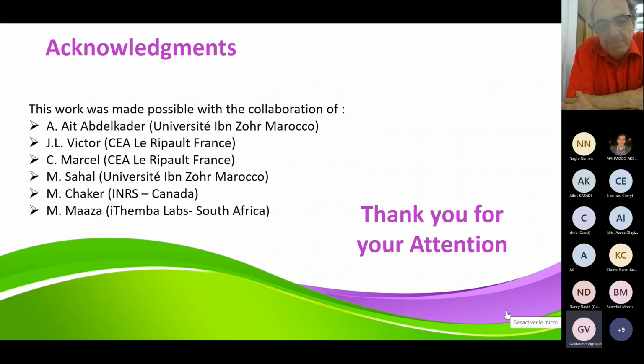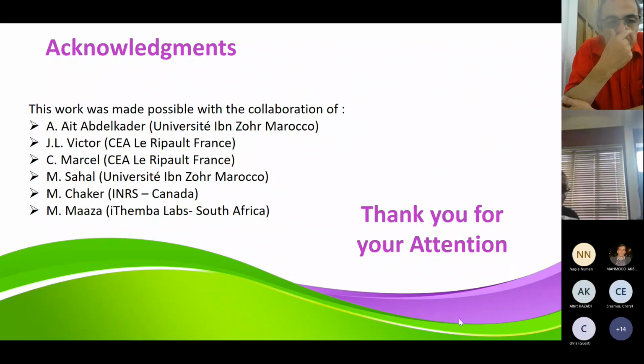Yeah, it's a very good point. It's clear that when you are doing it like this, you could have in some places some clusters of tungsten, and it's not very clear whether it is really very well uniformly distributed. Although, when you look at the X-ray diffraction pattern, there is no specific sign of metallic clusters of tungsten. Normally, you should be able to see some of them, unless they are very small. But in this case, we didn't see any specific contribution of tungsten in the scattering pattern, and it is impossible, from a very low concentration of tungsten, to calculate from the diffraction pattern the content of tungsten in the films. This is too small a content of tungsten.